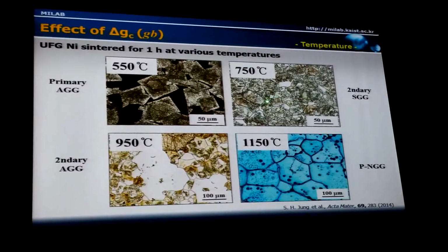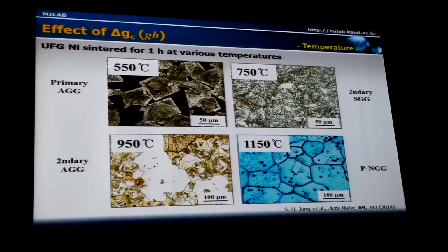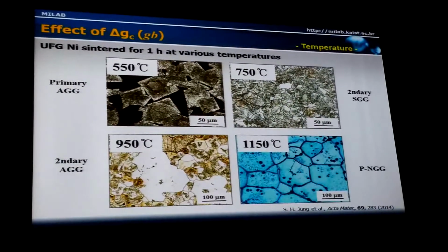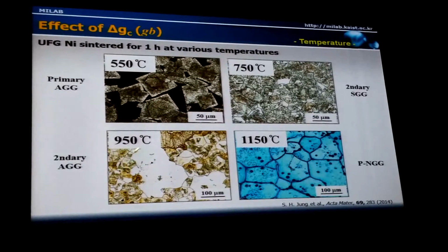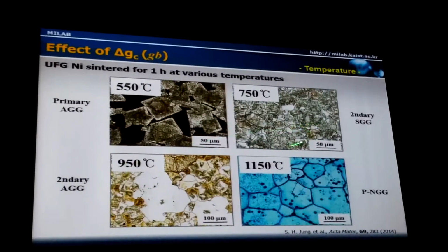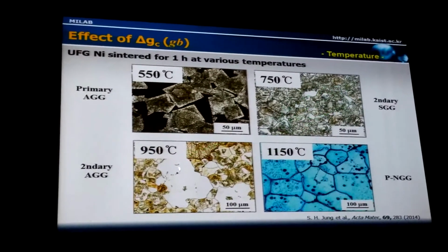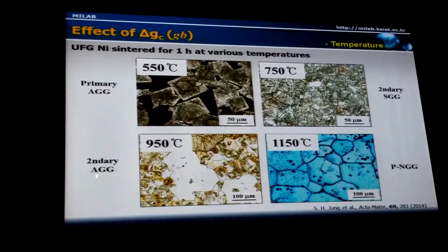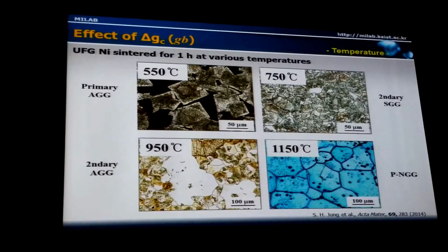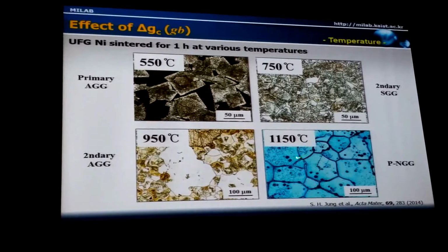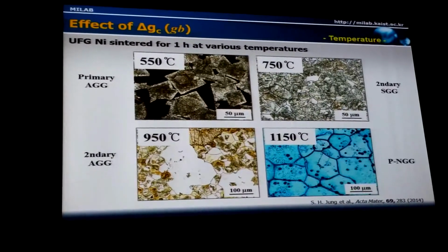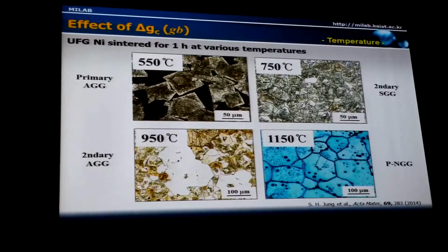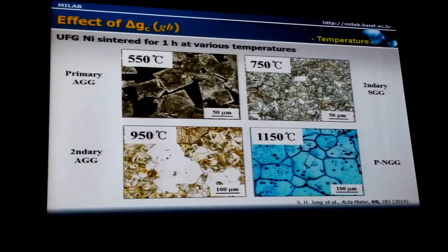When we held this sample for a longer time, there was essentially no change in microstructure, and grain growth did not occur. But at 950, among the impinged grains, an abnormal grain formed. That means secondary abnormal grain growth occurred at 950. And at 1150, there is quite normal grain growth, a normal microstructure.